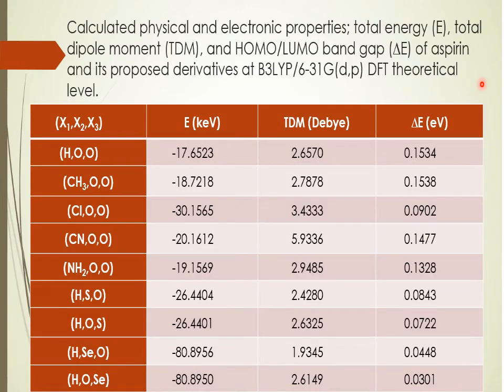This table illustrates the calculated physical and electronic properties. Total energy of aspirin is minus 17.6523. From the groups that substitute at X1, chloride has the lowest total energy and is the most stable one. And from the other positions, selenium in X2 and X3 has much lower energy and is the most stable compound.